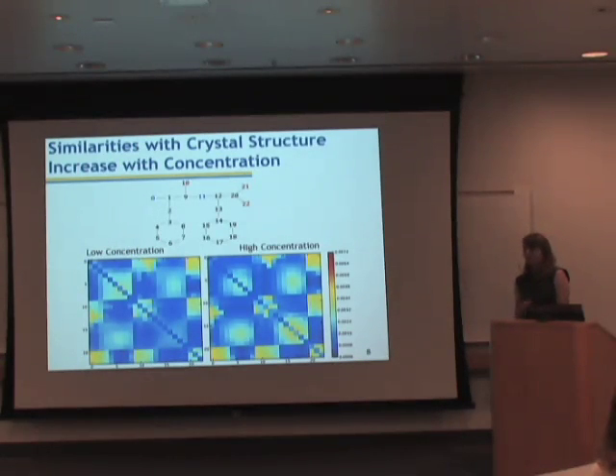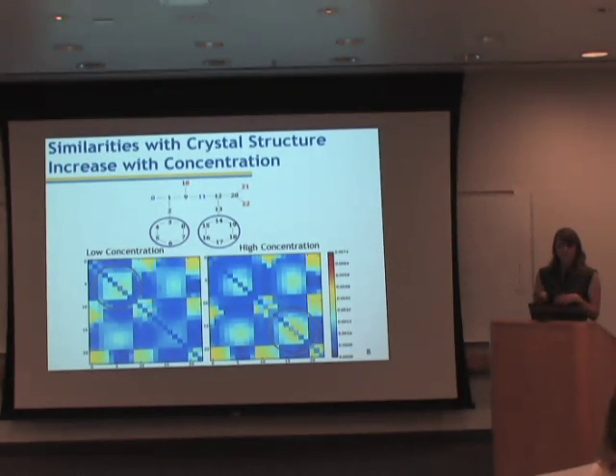The next thing we wanted to evaluate was the effect of local concentration on peptide aggregation. What we find is that as we increase from a low concentration to a high concentration in our simulations, the side chain interactions start to change, from first ring interactions to second ring interactions. We conclude from this data that as we increase the local concentration of the peptide, it starts to more strongly resemble the crystal structure.